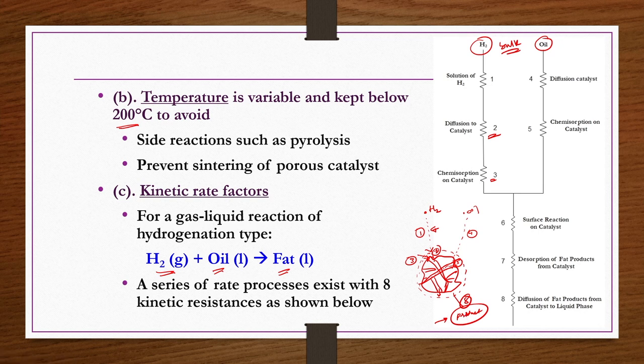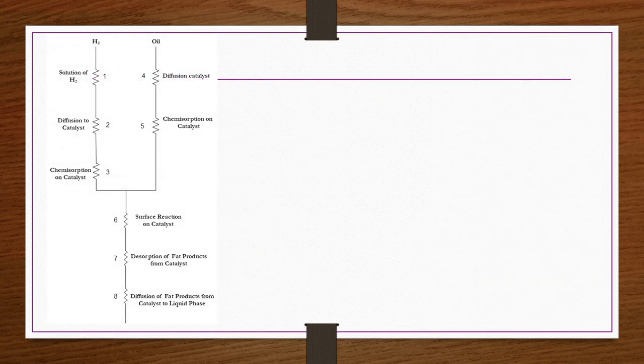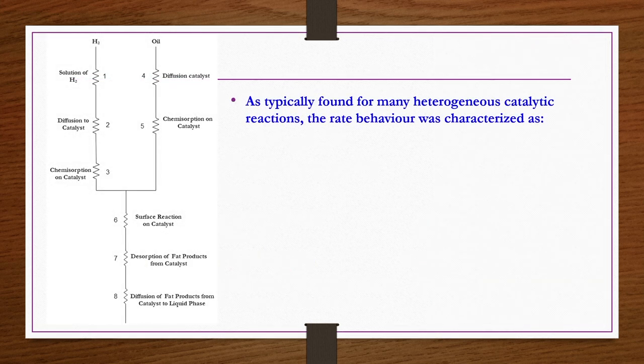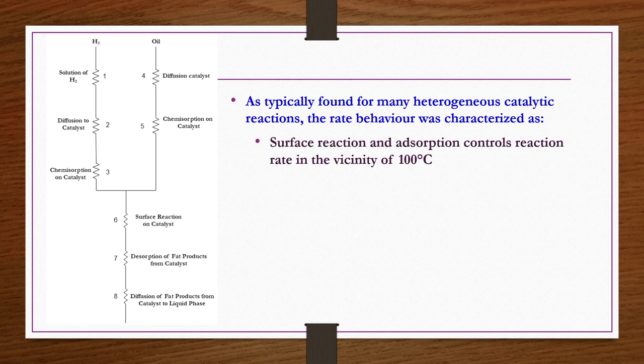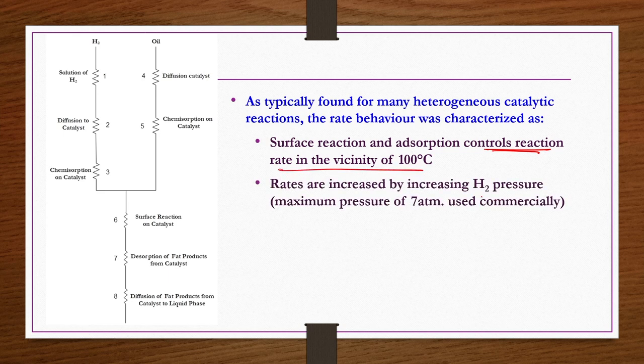Out of this, step number 1 and 2 are the rate limiting steps because they require higher energy to occur. The same is shown here again. As typically found for many heterogeneous catalytic reactions, the rate behavior was characterized as surface reaction and adsorption controlling the reaction rate in the vicinity of 100 degree centigrade, and the rates are increased by increasing H2 pressure, maximum up to 7 atmosphere used commercially, right?